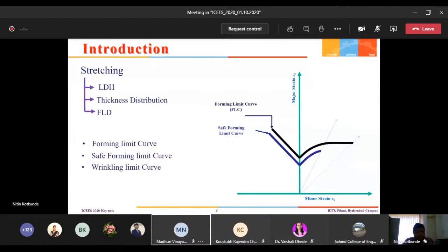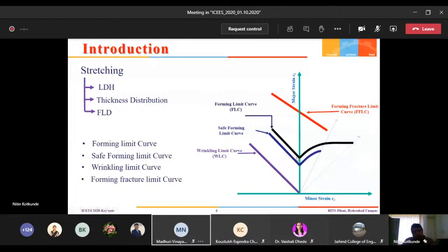As I mentioned, wrinkling is a serious issue in all stretch components or sheets, because these are all thin sheets, 1 millimeter, 1.5 millimeter, or 2 millimeter maximum. So it has a tendency to fold or wrinkle at many places. We need to determine the wrinkling limits also by using this diagram. Usually the wrinkling tendency happens in the uniaxial region. The left side of the vertical arrow shows the uniaxial region, the right side shows the biaxial region, and this vertical line is under plane strain condition. And obviously the fracture is substantially above the necking tendency.